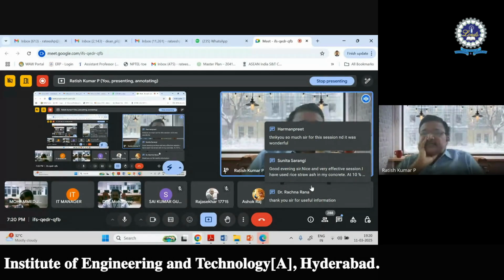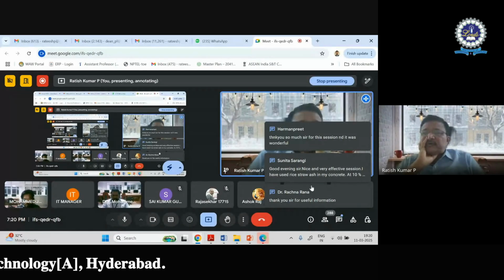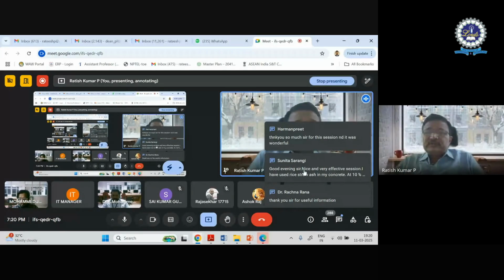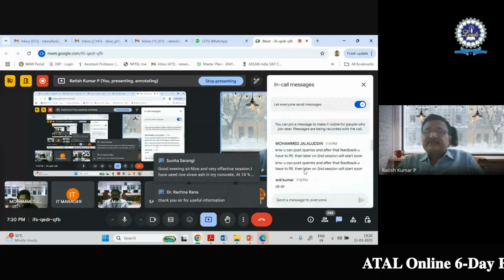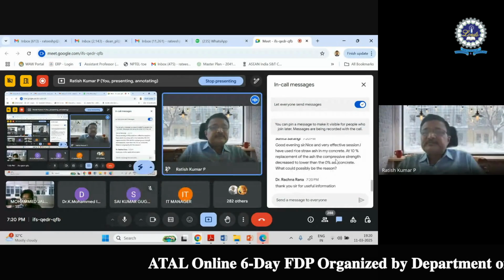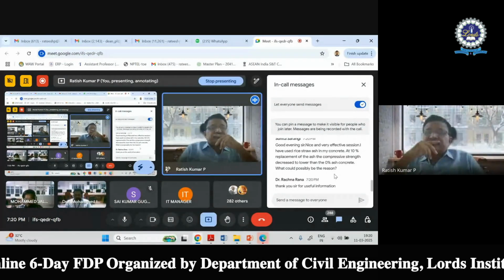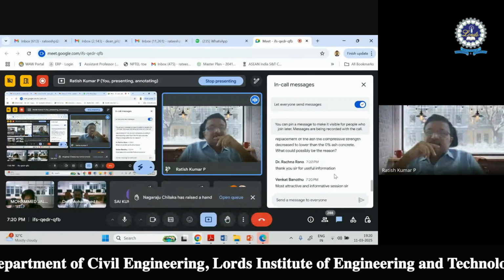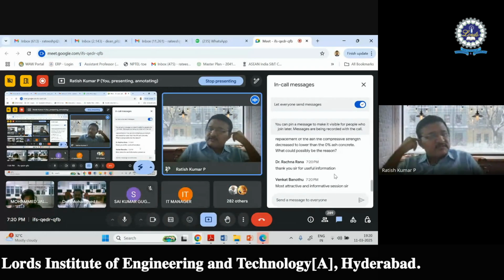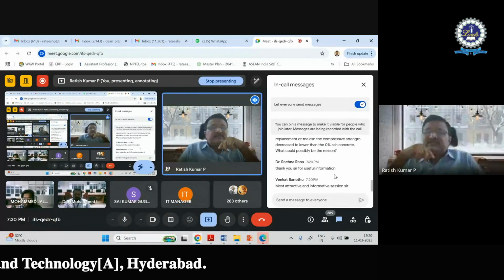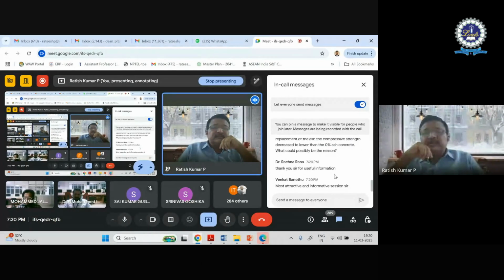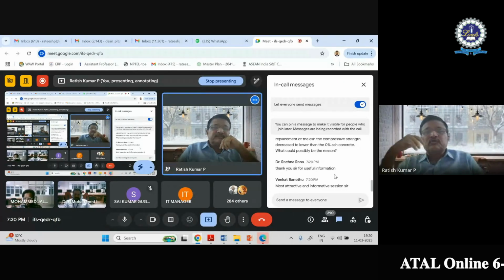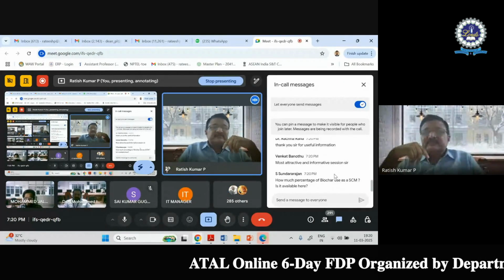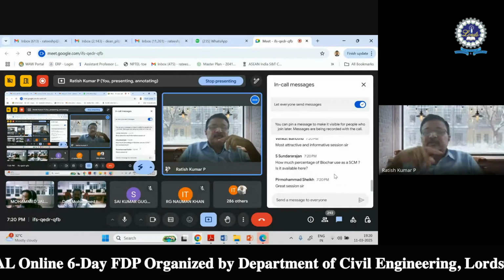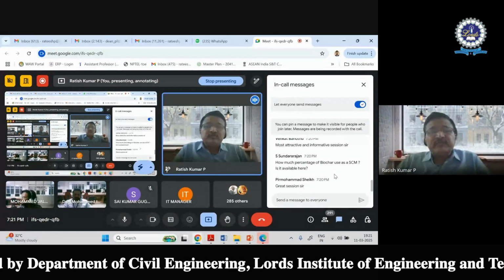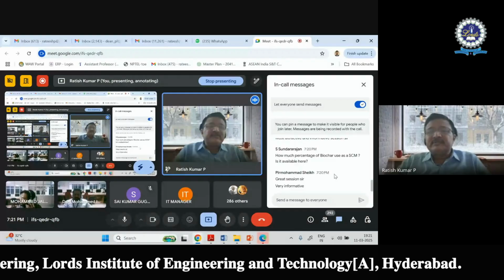Somebody is saying that it is nice and very effective. I have used rice straw ash in my concrete at 10%. At 10% replacement of the ash, the compressive strength decreased. See, the straw or fiber is not supposed to increase the strength actually. The strength in terms of flexural strength and tensile strength is going to increase with fibers. You don't expect an increase in the compressive strength per se. There could be a marginal increase, but you don't expect an increase in compressive strength when you use fibrous materials. It's not meant for that.